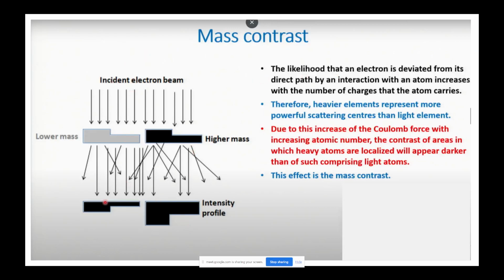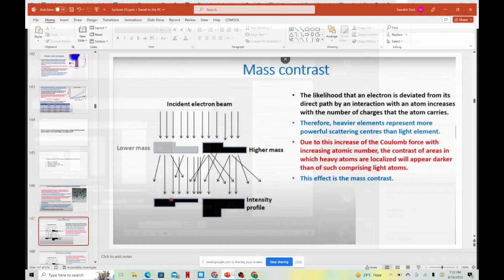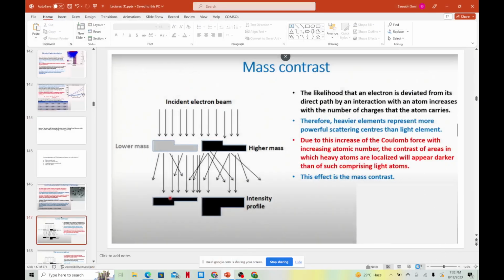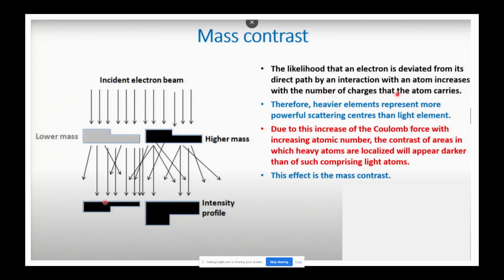So the likelihood that an electron is deviated from its direct path by an interaction with an atom increases with the number of charges that the atom carries. Therefore heavier elements, this is your heavy element, represent more powerful scattering. Here you can see the electron beam is straight, and it is scattered at a high angle by the heavy atom centers, compared with the light element. It is not scattering much, so here you will not get much scattering.